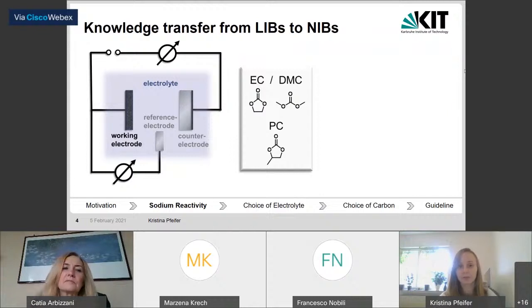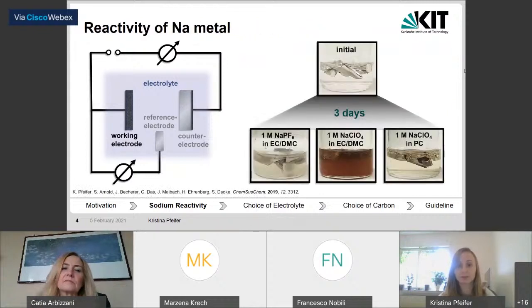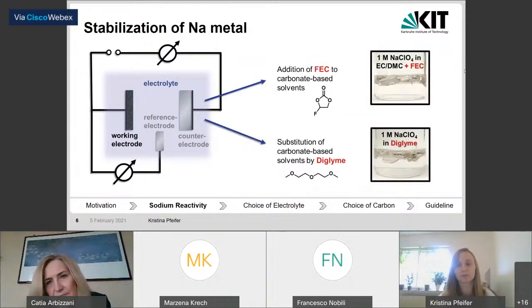Because of the enhanced reactivity of sodium, we tried to find out if it has an effect. And what we saw was a drastic change of the electrolyte when placing sodium inside. That means that the results you get from these measurements are not reliable. Nevertheless, we were able to stabilize the sodium metal in the different electrolytes by either adding FEC to the carbonates or replacing the carbonates by diglyme. Still, we have to find out how these electrolytes behave in an electrochemical cell during cycling.